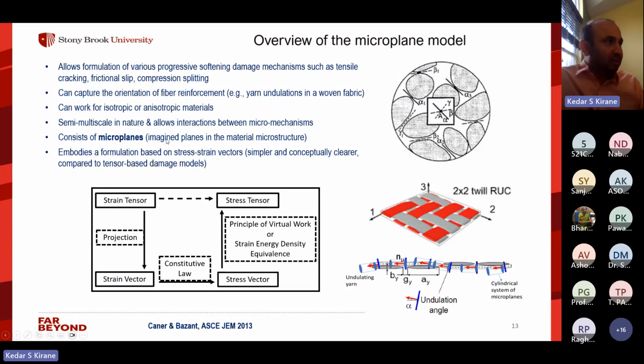So in microplane models, what is done is you imagine that at a given material point, there are several microplanes. These are imagined planes within the material microstructure. And this is kind of analogous to crystal plasticity type models used in metals, except in crystal plasticity, the slip planes are well-defined planes, whereas these microplanes are randomly oriented. And then what is done is you project the strain tensor onto these microplanes and you then get the strain vector. And you define the constitutive law corresponding to individual damage mechanisms in terms of these stress strain vectors. Now, because these are vectors, it becomes very easy to define various damage mechanisms like tensile cracking or frictional slip, local shear, and things like that.